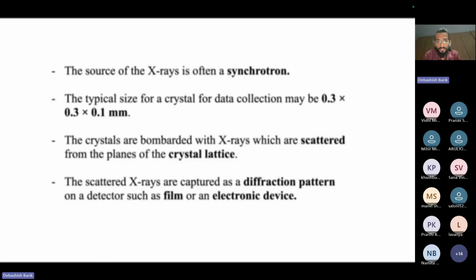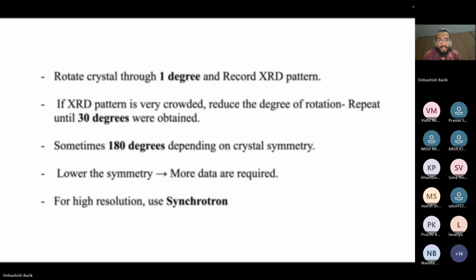The crystals are bombarded with X-rays, which are scattered from the planes of the crystal lattice. The scattered X-rays are captured as a diffraction pattern on a detector, such as film or an electronic device. Rotate the crystal through 1 degree and record the XRD pattern. So the crystal was rotated by 1 degree, and every pattern was recorded at each 1 degree.